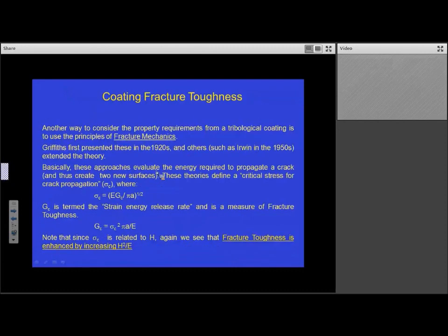There are also reasons of fracture mechanics. I won't go into it, but those of you who are familiar with fracture mechanics will know that work by Griffiths and Irwin, etc., define a critical stress for crack propagation, sigma c, defined by this expression, and Gc is termed the strain energy release rate, and it's a measure of fracture toughness. And you can see here that Gc is sigma c squared pi a over E. So again, we see from fracture mechanics considerations that H squared over E also gives an indication of the ability of a surface to prevent fracture. So yet another H over E ratio, which leads us to the belief that the ratio of hardness and modulus are important in defining the wear resistance of the surface.